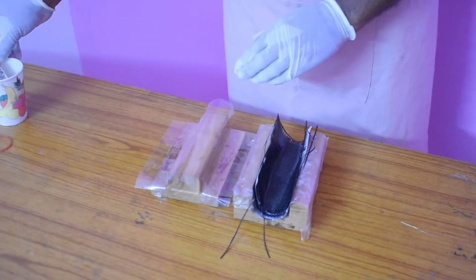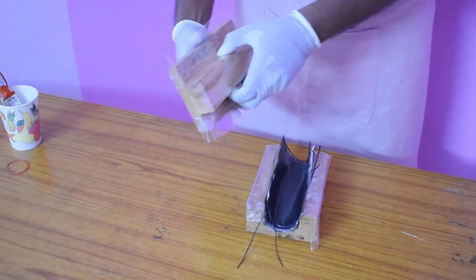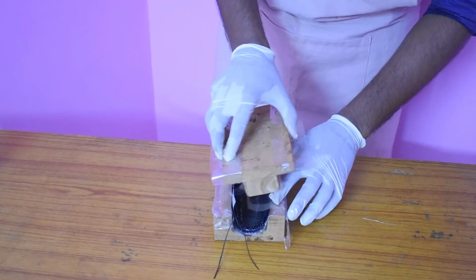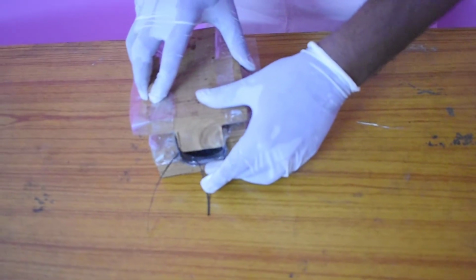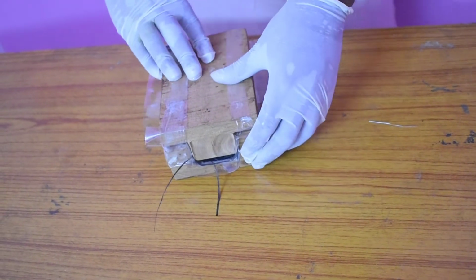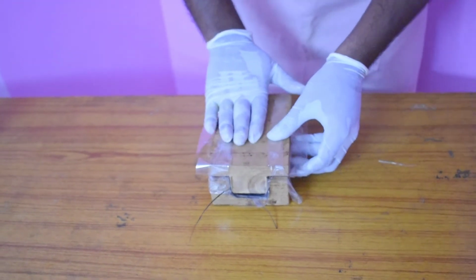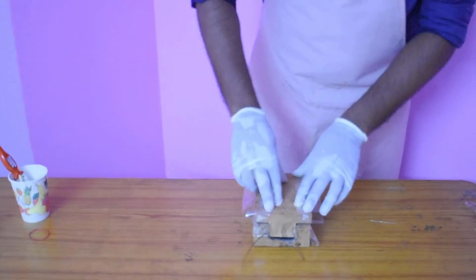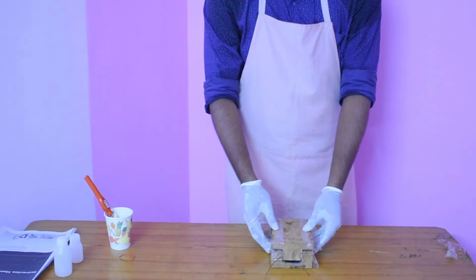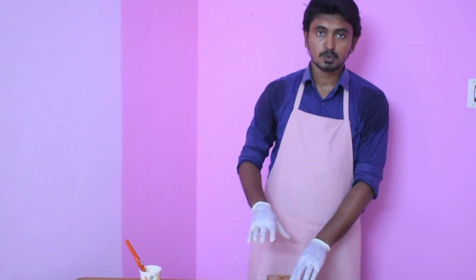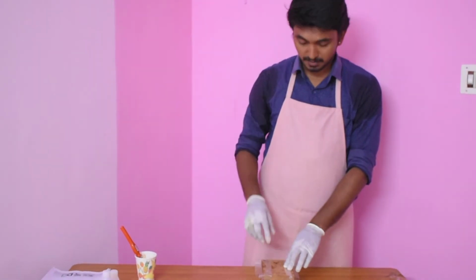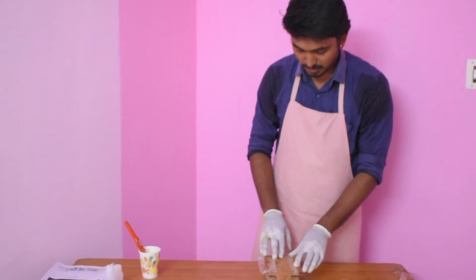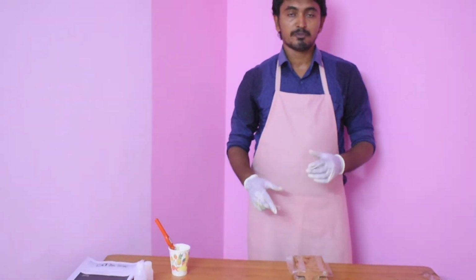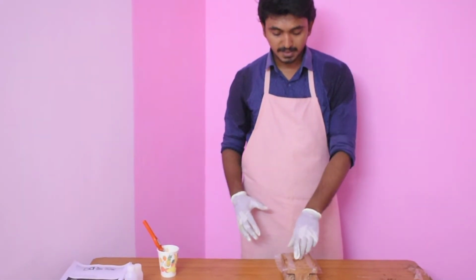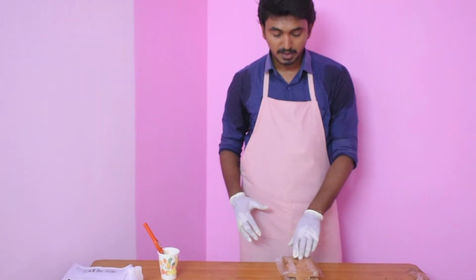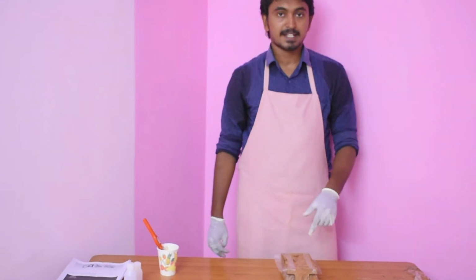Keep these things aside. Now we have to close the top of the main mold. We have to be careful while closing the mold. Just give some even pressure on the mold so that the resin can spread equally. Once we close the mold, we have to give a load of 1 kg or 2 kg to get a fine, quality product, and it also helps the resin to spread equally. The curing will take around 4 to 6 hours. While curing, there should not be any external disturbances or obstacles given to the product, as it may affect the curing. So let's see this after 6 hours.